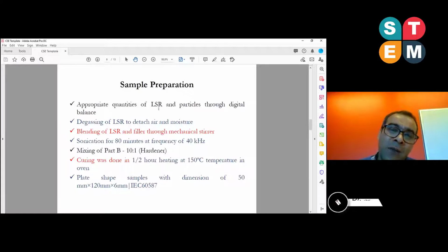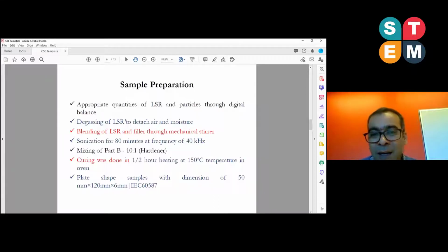We have to add our additives in the polymer, but we have to be careful. The degassing step should be taken very carefully, because we don't want any moisture or air trapped in the insulation sample, because if air is trapped in the insulation, that can start electrical discharges in it. So we use the mechanical mixer, and after that we have to use the sonication.